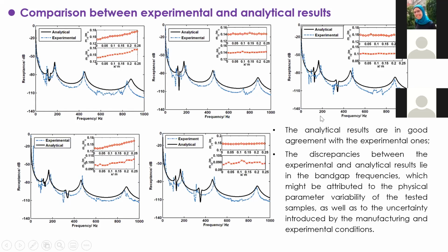These discrepancies, we think, might be attributed to the physical parameter variability of the tested samples, as well as uncertainties introduced by the manufacturing and experimental conditions. For example, since additive manufacturing creates the structures layer by layer, some small pores and defects are introduced during the manufacturing process. So some variabilities of the physical parameters are unavoidable, and that's why we said these discrepancies should be related to physical parameter variability.